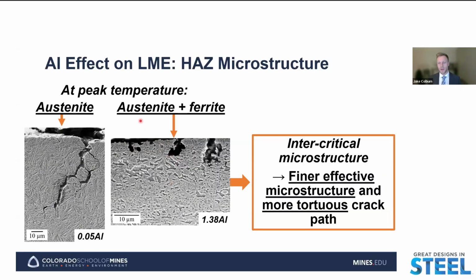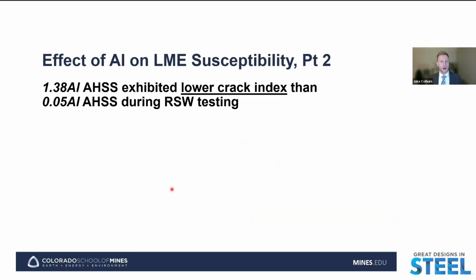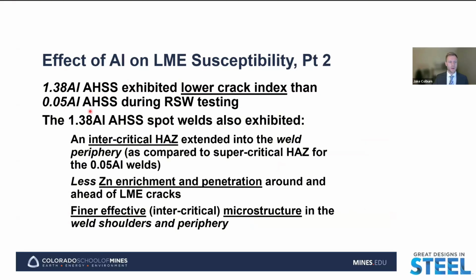So at the austenite plus ferrite, we can have this finer effective microstructure, as well as potentially also this more tortuous crack path that's going to make it more difficult for these cracks to propagate and grow. And so putting, again, some of those conclusions together, we see that the high aluminum alloy exhibits a lower crack index during spot welding testing than the low aluminum alloy.